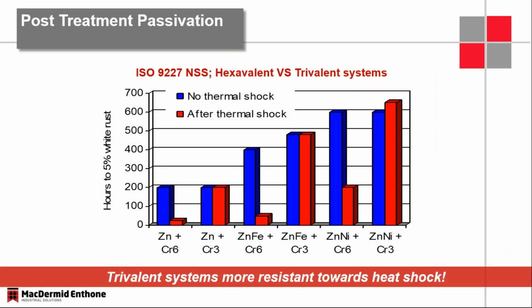So you can see here a little quick example about some of those corrosion resistance. First, we're looking at the zinc with hexavalent chromate. You look at heat treatment, salt spray after heat treatment, and you can see that the trivalent and zinc before and after is about the same. And then when you start getting into the hexavalent chromates, whether it's zinc iron or zinc nickel, the red bar is after thermal shock. And you can see a significant difference in the performance as it's related to heat treating. Now, whether that's baking for hydrogen embrittlement or whether that's service life, under hood applications, trivalent passivates are going to perform better than hexavalent chromates in heat applications.